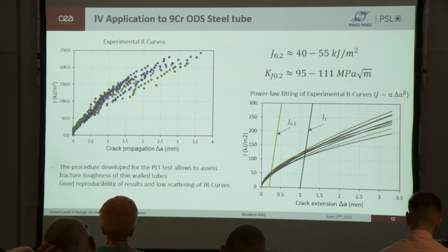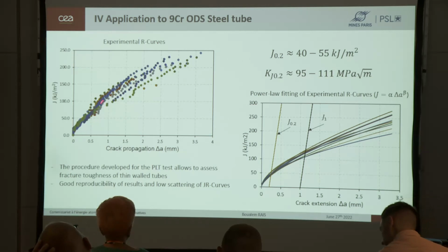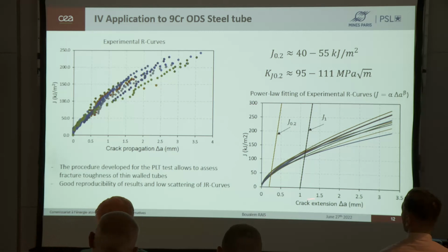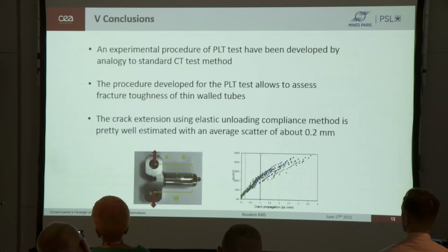Now, when plotting the raw resistance curves as obtained experimentally, we can see that we have a good reproducibility of our results with a very low scatter. So by fitting these curves by a power law as recommended by the ASTM standard, we can determine J 0.2, for example, of 40 to 55 kilojoule per square meter for this ODS steel tube. So to conclude, we developed an experimental procedure to assess the fracture toughness of ODS fuel claddings, following the ASTM 1820 for CT specimens. And this procedure can be applied to thin wall tubes. And using the unloading compliances, we can have a good estimation of our crack lengths with a certain scatter. So thank you for your attention.